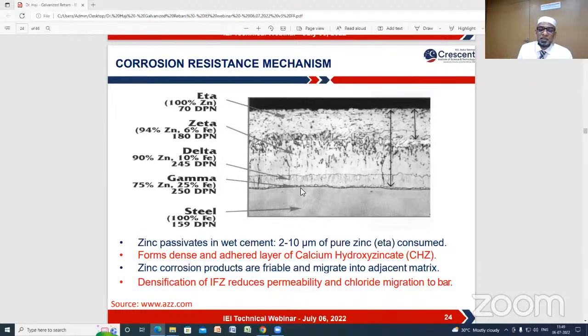So when the cement reacts with the topmost pure zinc, a passivation layer is formed at the interface between the galvanized rebar and the cement concrete. When this passivation layer is formed, it will offer very good protection to the steel. So it will be taken care of for a longer period.